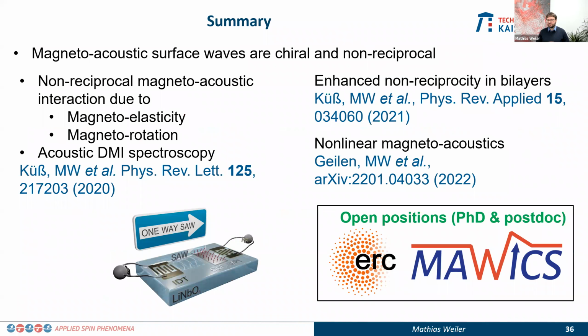So with that, I'd like to come to the end and conclude. In summary, I hope I could show you that these magneto-acoustic waves are interesting because they can be chiral and non-reciprocal. For this non-reciprocity, there are two important effects that contribute to it: magneto-elasticity and the magneto-rotation effect. We can also use such a setup to acoustically do spectroscopy of the strength of the Dzyaloshinskii-Moriya interaction. We can enhance the non-reciprocity by enhancing the spin wave non-reciprocity in bilayers. We can also go and study nonlinear interaction effects.